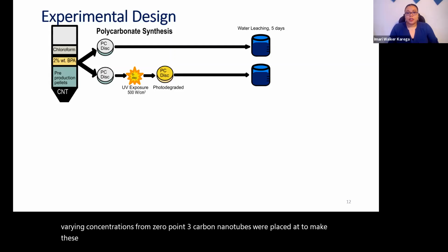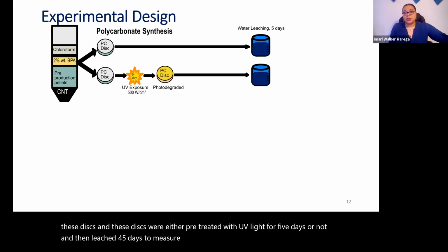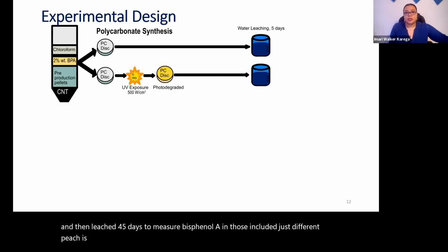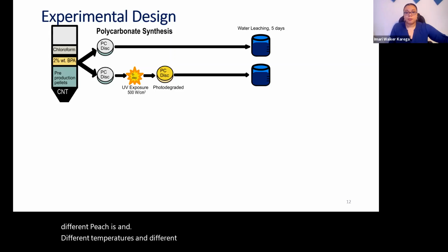These discs were either pre-treated with UV light for 5 days or not, then leached for 5 days to measure bisphenol A release, across different pHs, temperatures, and NOM content in the water.